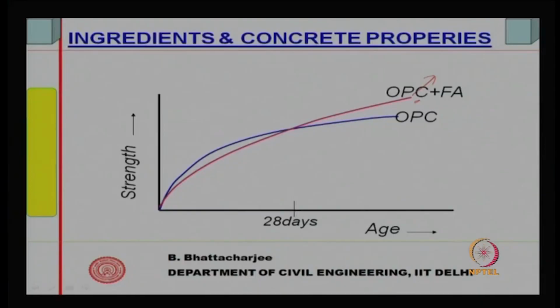So, by about 28 days, the fly ash can be consumed gradually by the lime in order to make the concrete more solid. The void space which was formed in the beginning would now be filled with hydration product, replacing the non-sealing precipitate of calcium hydroxide. Calcium hydroxide is a sparingly soluble non-sealing precipitate. So, this reduces the voids, and since the pore space and capillary pores are reduced, there is an increase in strength, since pore sizes become finer. So, both ways, long term strength is much better with fly ash.